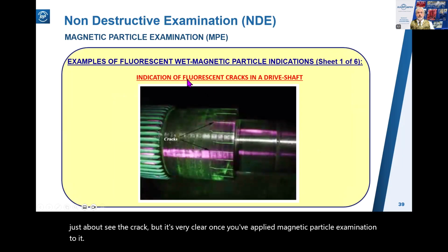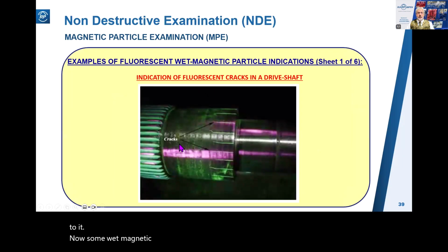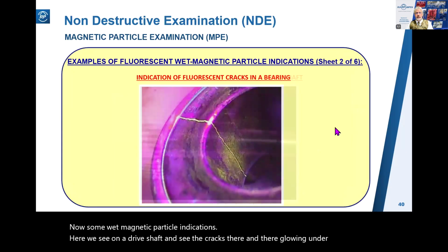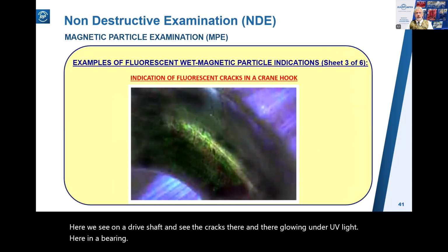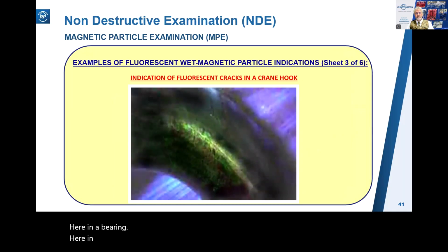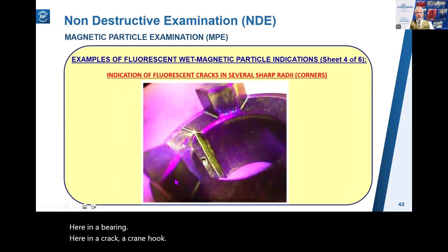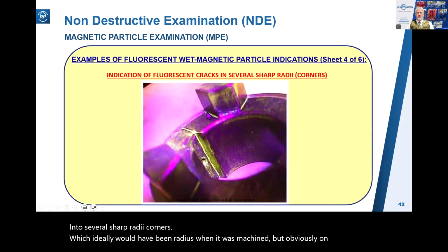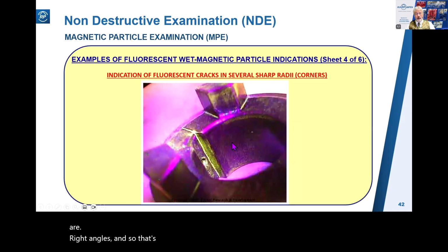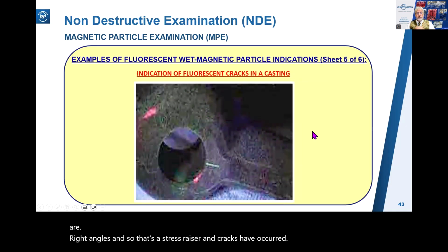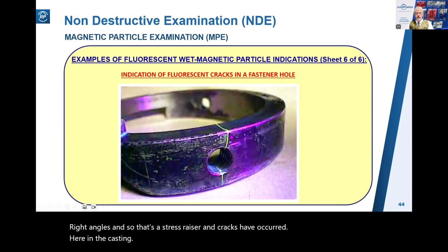Now some wet magnetic particle indications. Here we see on a drive shaft, you can see the cracks there and there glowing under UV light. Here in a bearing. Here in a crane hook. And here are several sharp corners, which ideally would have been radiused when it was machined, but obviously on this one they are right angles, and so that's a stress raiser and cracks have occurred. Here in a casting, and again in a fastener hole.